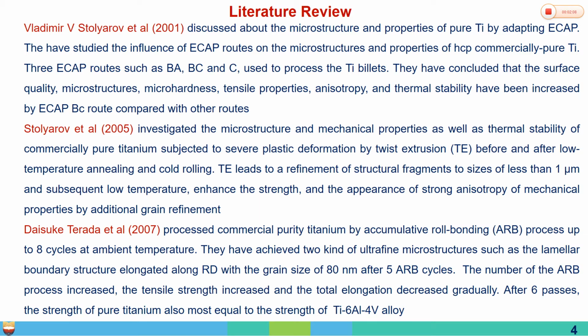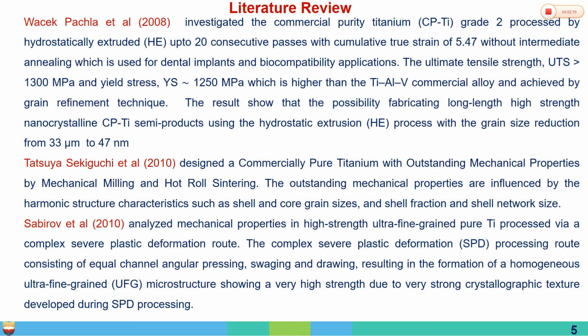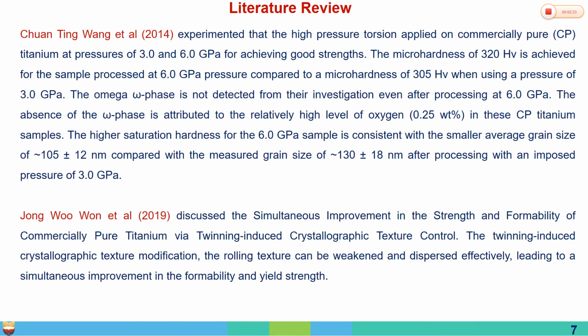Based on this work, different techniques have been used in order to achieve the strength of commercial pure titanium equal to the strength of Ti-6Al-4V. Another researcher investigated commercial pure titanium hydrostatically extruded up to 20 consecutive passes. They achieved a good yield strength of 1250 and 1300, up to the ultimate strength of the material.